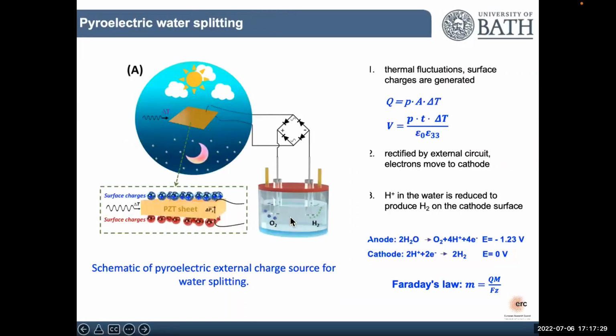And as Haito mentioned, I was making devices, external devices, and I knew that they would generate high voltages. So could I actually use them to induce water splitting? So this is just a ceramic element that's being subjected to some heating and cooling. So the polarization is changing, is modulating as I heat and cool. These surface charges from my external device are now free to take part in an electrochemical reaction. It's an AC. Remember, current is flowing back and forth as the polarization increases and decreases.